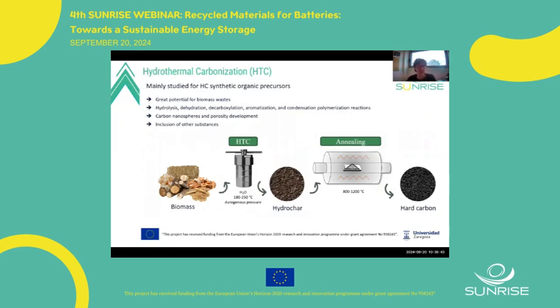I want to emphasize another carbonization method to produce hard carbons: hydrothermal carbonization of the biomass. For now it was mainly studied to produce hard carbon from synthetic organic precursors, but we think there is great potential to use it with biomass wastes or agronomical wastes. This process consists of carbonizing the biomass in a closed vessel with water, mainly water, at low temperatures and in autogenous pressures.